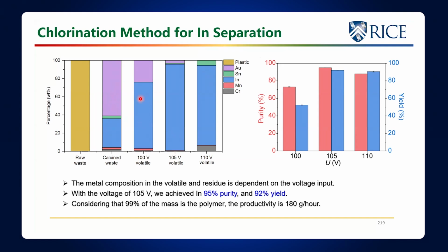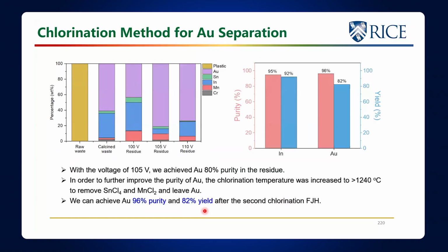But if you do it at 105 volts, we drive all of this to completion, and we get almost all indium here. There's going to be a little bit of other things in there. So at 105 volts, we're going to get up to about 95% purity, and on the yield, it's going to be 92%. Considering that 99% of the mass was polymer, the productivity rate is 180 grams per hour of this electronic waste that could be recycled.